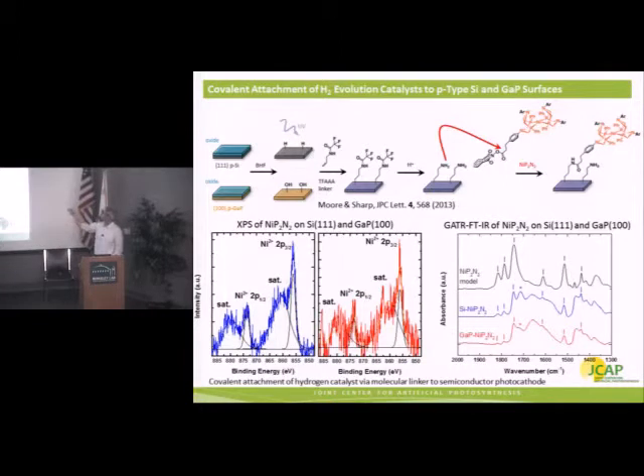Following deprotection, we can react this with a nickel P2N2 molecule bearing an activated ester tethering group, and that results in a construct such as this. We can verify that this is formed similar to how we draw it using XPS. Here we see the nickel 2p region of the XPS spectrum that indicates that we have nickel in a 2+ configuration, consistent with what we would expect.